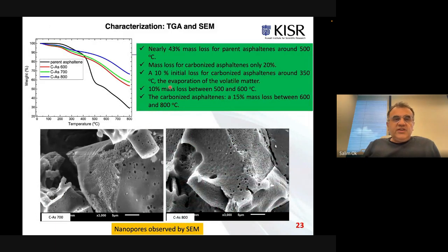As you can see here, compared to raw asphaltene, thermally speaking, the carbonized asphaltenes are pretty stable. That's the first good news for us. Second, when we focus on the porosity of the carbonized materials, as you can see here, the carbonized asphaltenes show pretty nice porosity.